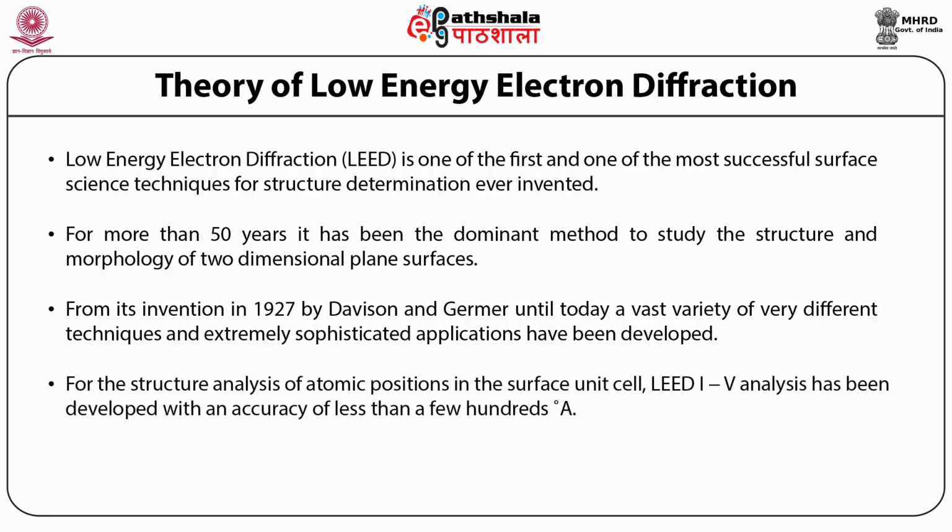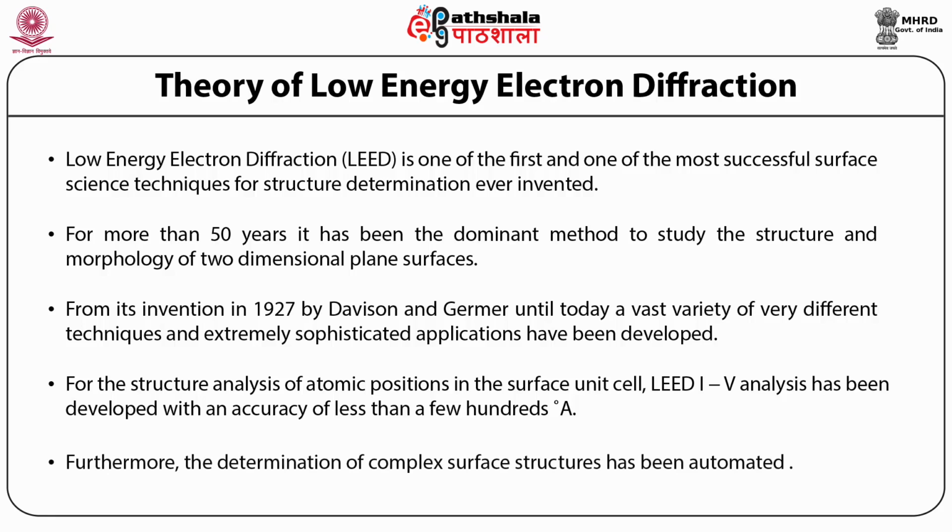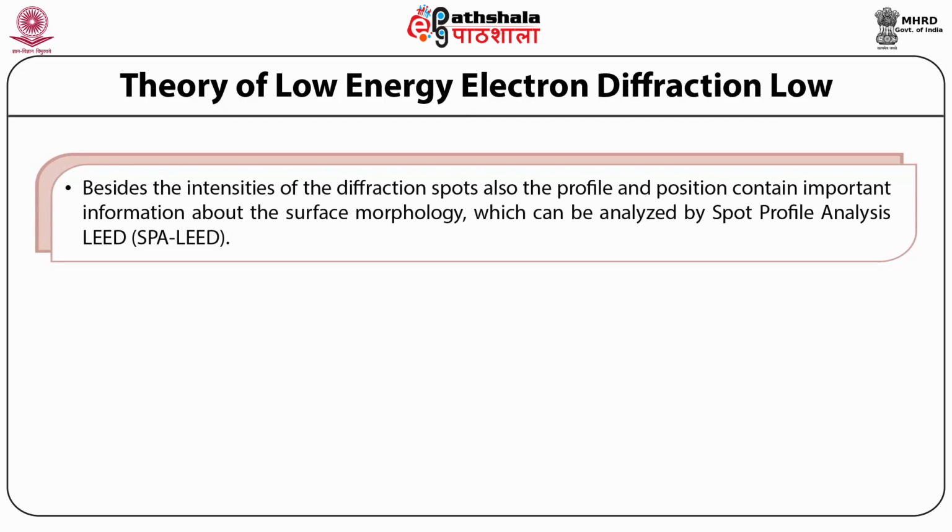For the structure analysis of atomic positions in the surface unit cell, LEED can analyze, and methods have been developed, with an accuracy of less than a few hundredths of an angstrom, which is an extremely accurate result. Furthermore, the determination of complex surface structures has been automated. Besides the intensities of the diffraction spots, the profile and positions also contain important information about the surface morphology, which can be analyzed by spot profile analysis LEED, that is SPA-LEED.